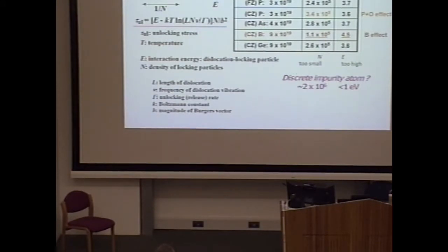One times 10⁵ per centimeter. This is rather low in comparison to discrete impurity atoms. If we assume that the discrete impurity atom density comes to 2 × 10⁶ per centimeter, and also the interaction energy is rather low, less than 1 electron volt. This is Malcolm's calculation. So he calculated many states, many structures.